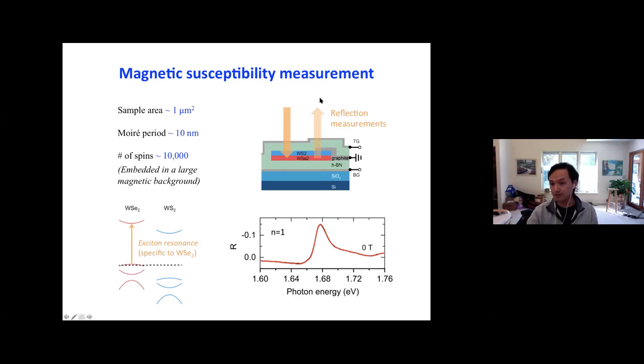And this is a reflection contrast spectrum example shown here. It's measured at zero magnetic field for both left and right-handed channels, meaning that we shine left and right-handed light, and we look at the difference. And you see almost no difference. The red curve and the black curve corresponding to each handedness of the light are almost exactly the same. That's expected because it's at zero Tesla. We did not apply any magnetic field, so the system does not break time reversal. The response is just the same for left and right-handed light. Oh, by the way, this is fixed at filling factor equal to 1 at the moiré state.